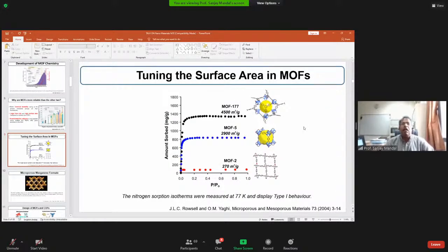Now, as I said, how do you tune the surface area? You just change the carboxylate in this MOF-2 to go to MOF-5. You go from 270 to 2900, and if you increase the length of this carboxylate, it goes to 4500. And this is how you can tune the surface area and pore volume.